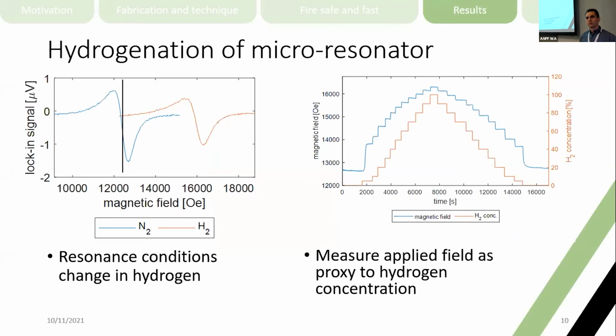And on the right-hand side, that is a little bit more application-driven. Here we measure in a time-resolved manner. How do we do that? We set the magnetic field and the microwave frequency, which we apply, to a fixed value. We then use a PID loop to control the magnetic field. So we control an electromagnet with a PID loop. And when we absorb hydrogen, the resonance shifts, and we set the PID to just keep the lock-in voltage at the same output signal. And we then measure the magnetic field and use that as a proxy of the hydrogen concentration in the environment. And we see here very nicely how we can differentiate between 5, 10, up to 100% of hydrogen.